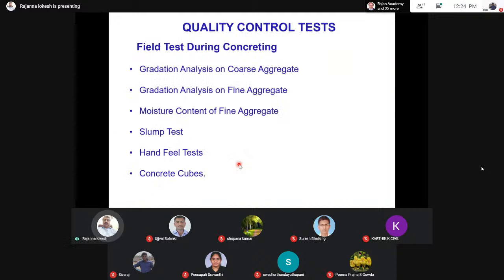So, what are the field quality control tests that are to be carried out? As I told, it can be gradation on coarse aggregates, fine aggregates. Moisture content for fine aggregate is a very important test that should be carried out before start of the work, so that any variation, any inherent moisture in the fine aggregate can be suitably reduced in water cement ratio, slump test, hand feel test, and concrete cube test.